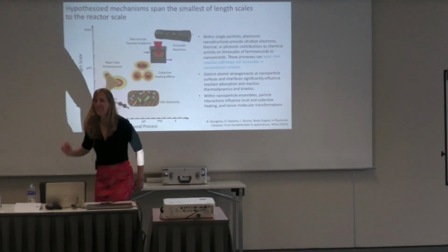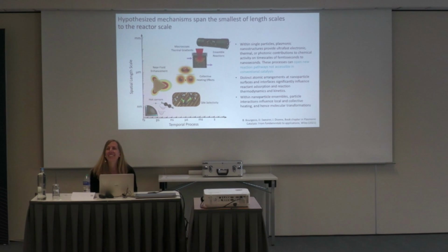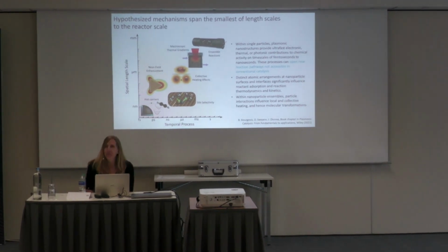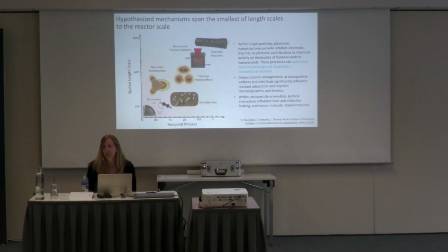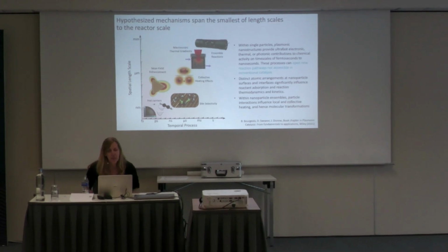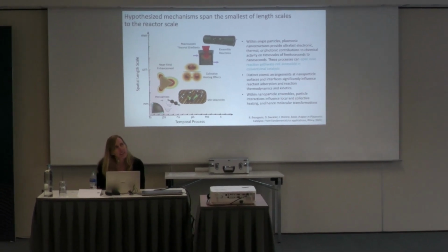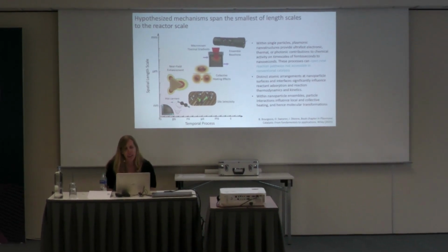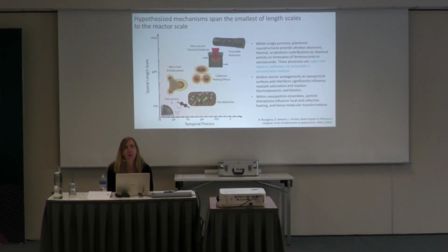I had one more question. Sure. You mentioned for CO2 reduction you were using gold palladium nanoparticles, right? But in the field of electrocatalysis, copper nanoparticles are commonly used. So why did you choose to go with gold palladium? Yeah, great question. Naomi Halas had some really interesting results of how using plasmon excitation of gold, she could get splitting of hydrogen. So it's a neat system to be able to use the combination of gold and palladium both for light absorption, but also for some of that controlled hydrogenation in the CO2 reduction process.